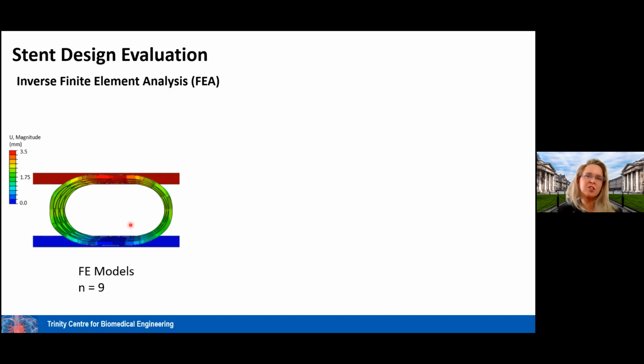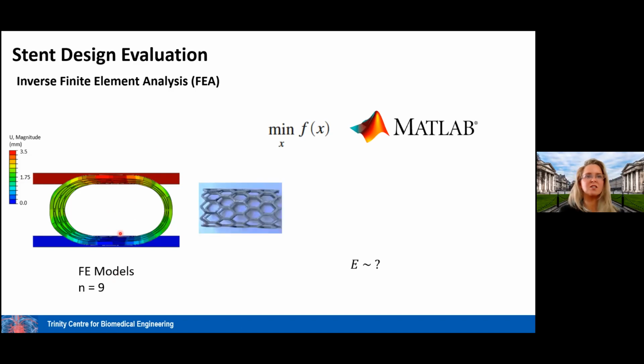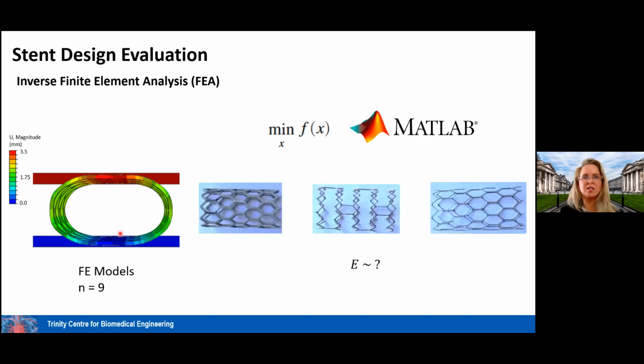So then we went on to see, well, when we print the stent, what is the stiffness of the titanium in its as-printed state? And that's quite a difficult thing to do. I mean, you can make small little coupons and test them, but again, it is very difficult to look at the impact then of even things like the angle that you print at and so on. So we decided to use what's called an inverse finite element approach, where we create a finite element model, which exactly replicates what we do experimentally. And we can iterate then using a minimization approach of the difference between what we see experimentally and what we see numerically by changing the Young's modulus of these stent designs that are created in our finite element model.